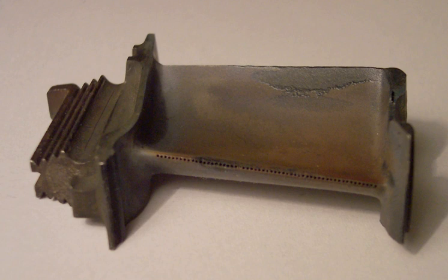The current, first-generation, thermal insulation layer is composed of 7 wt% yttria-stabilized zirconia (7YSZ) with a typical thickness of 100 to 300 micrometers. Yttria-stabilized zirconia is used due to its low thermal conductivity, 2.6 W/mK for fully dense material, relatively high coefficient of thermal expansion, and good high temperature stability.